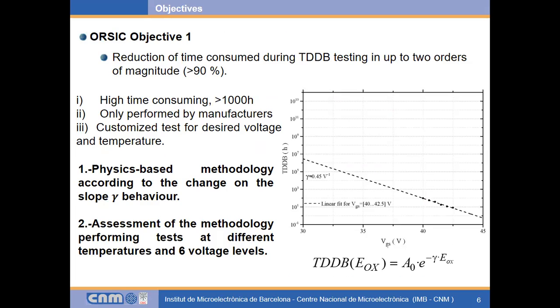Well, now let's describe the first objective of this project, which is the reduction of the time consumed during TDDB tests by up to 2 orders of magnitude. Such tests are highly time consuming, in the order of more than 1,000 hours, and are only or mainly performed by manufacturers for qualification purposes. Such data are not usually available to the final user, and we would like to propose a customized test for final hardware engineers to perform a fast TDDB test, and to extrapolate results to their final application temperature and voltages.